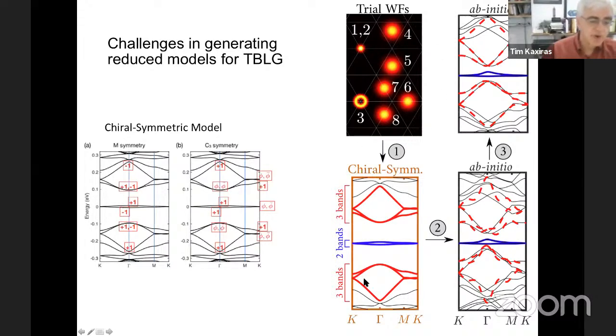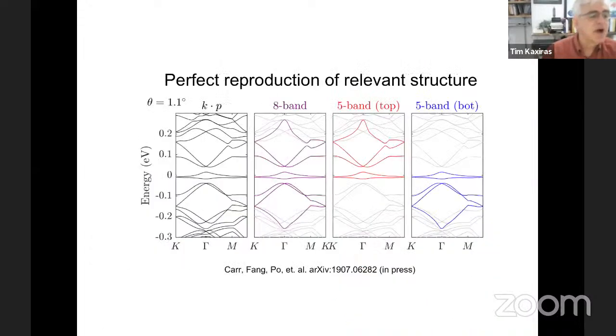Okay, so these 8 states produce this band structure in the chiral symmetry, and then we adjust the parameters of the Hamiltonian of these 8 states, to make sure that they fit very accurately the band structure of the ab initio calculations. Because these states do not reproduce the band structure of the ab initio calculations without adjusting their parameters. So having done this, we produce the following picture. So the full band structure is shown here. The band structure fitted with 8 bands is shown here, which is very, very accurate for a reasonable range around the Fermi level. Just keeping 5 bands, the 2 flat bands and 3 bands above, the 5-band model is this. Just keeping 5 bands with 2 flat bands and 3 below is this. But going to just 2 bands cannot reproduce this picture. That's the message that I want to get across.